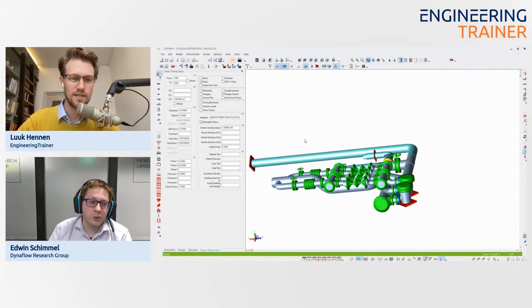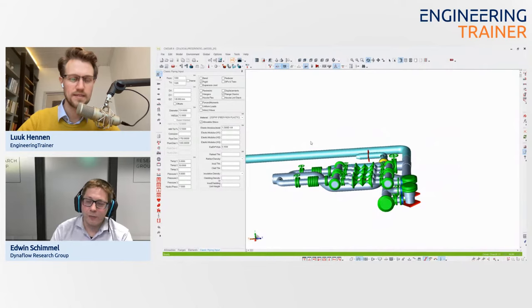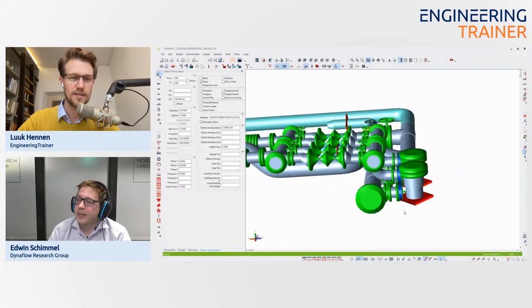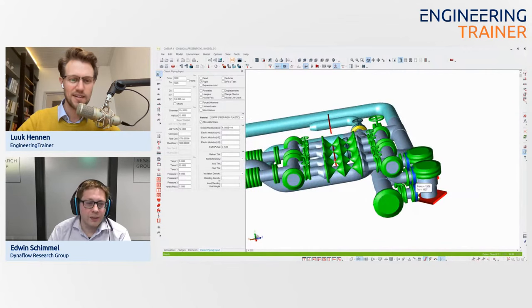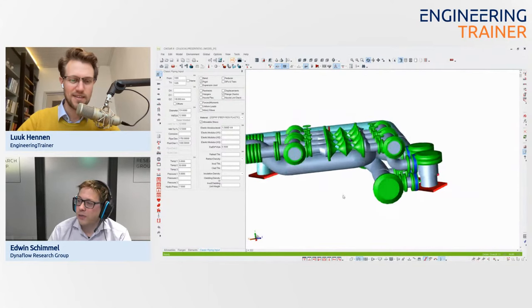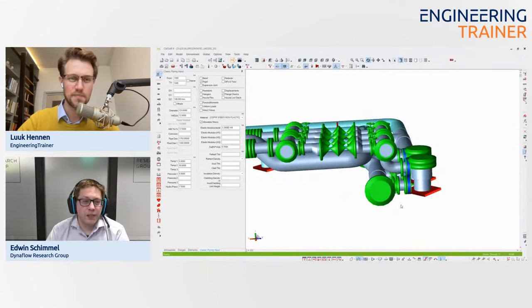Of course, the filters are the most critical component, or not the filter itself, but the nozzles are the critical components in the study. So here, the system has bellows, expansion joints with tie rods. And maybe that's also something specific for fiberglass. Expansion joints in a steel piping system are made from steel themselves, like harmonic. But with fiberglass, the bellows are often rubber, because if you have fiberglass, which is very flexible, and you introduce a steel expansion joint or bellow, it's still quite stiff. So with fiberglass, you use a rubber bellow, where the stiffness is lower, and that's relatively better to use with the fiberglass.